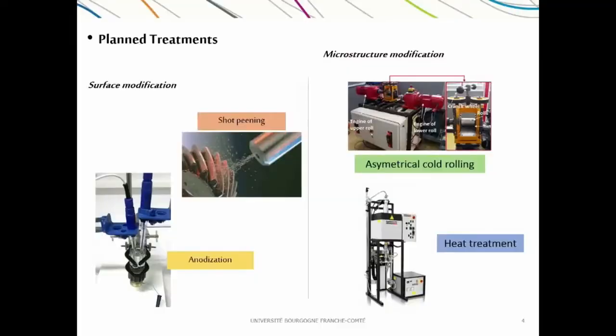In order to avoid this phenomenon, we apply different treatments. We distinguish shot peening, to introduce compressive stresses on the surface of the material; anodization, to create an oxide layer on the surface of the material; asymmetrical cold rolling, for work hardening of the material and to change the crystallographic orientation of grains; and heat treatment to recrystallize grains in the material.